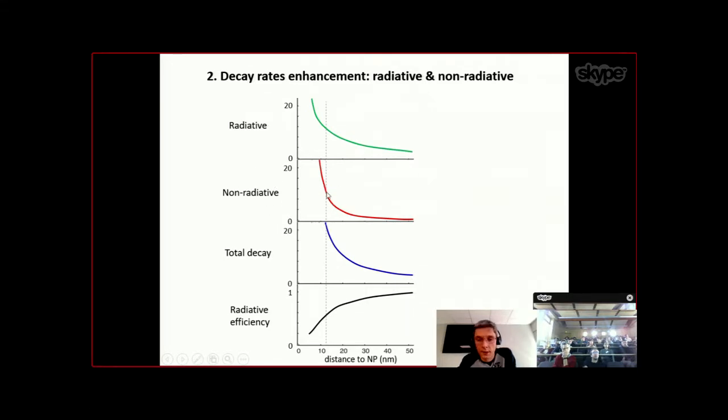As we have seen, the nanoparticle, it's metal, it can absorb energy. You have an electron flux into the nanoparticle, so you have a current, and then you have ohmic losses. Every time you have a current onto a real physical object, it's not superconducting, then you have a resistance, and then you have ohmic losses. Light energy is lost into heat.